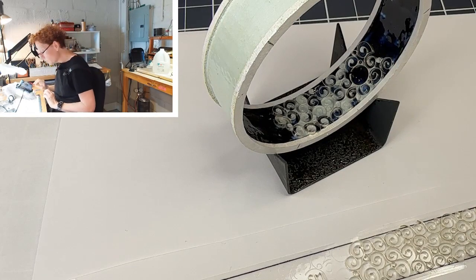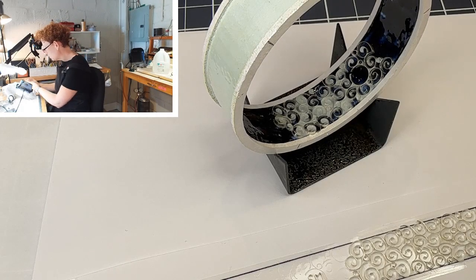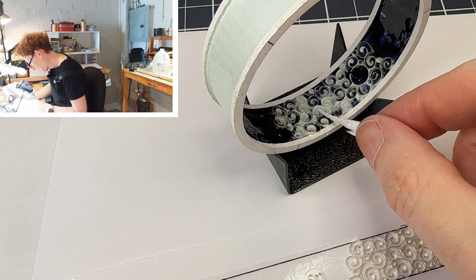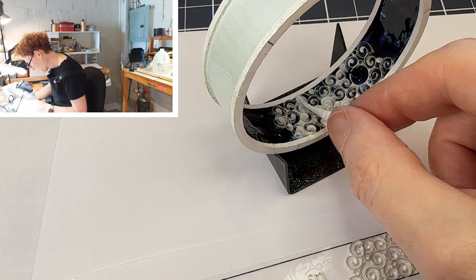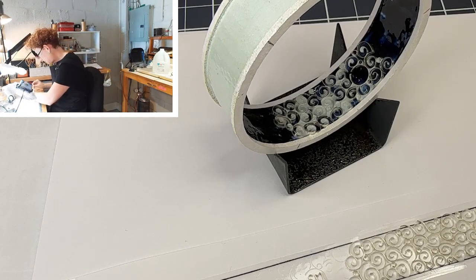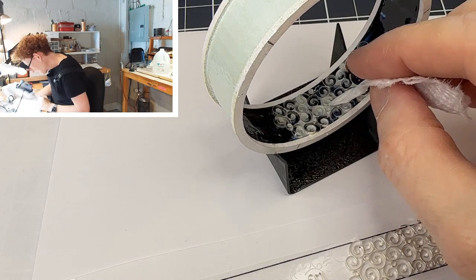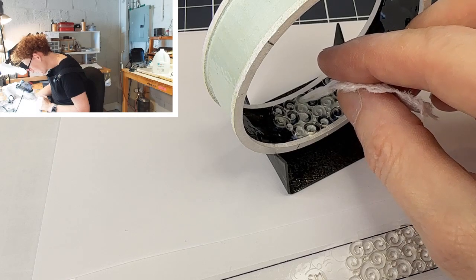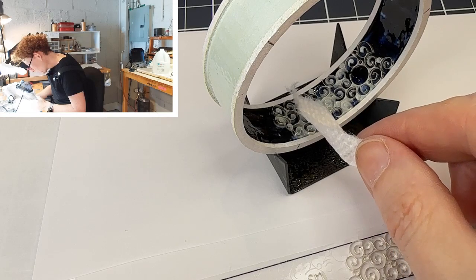That is good. I'm going to take a little moment. There's a lot of kind of wet glue, so I am going to wick up a little bit of that glue. It's going to be a huge tiki torch in the kiln at this point with this amount of glue. Very exciting. That'll be something to look forward to, but it will dry faster if I wick some of it up. But it's harder to wick the glue. It's just thicker, and I don't wanna mess up the wires.